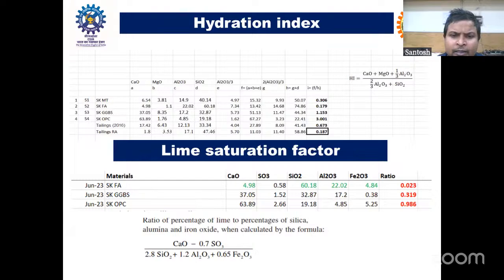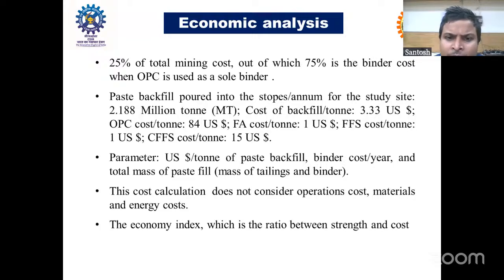So there are different studies we do, like comparing with hydration index and lime saturation factor. And there is one part we also did for a particular mine, which earlier was using cement as a complete binder. Normally in backfilling application, if you are simply using cement as a sole binder, that means you are spending more, and backfilling is itself a costly affair, out of which 75% is the binder cost. So the target was to reduce the backfill cost and to use alternate binders so that cement can be replaced.